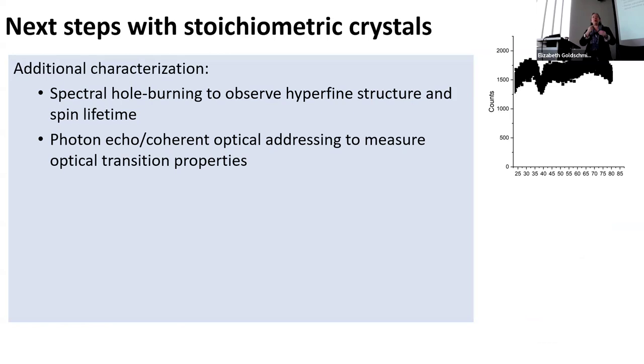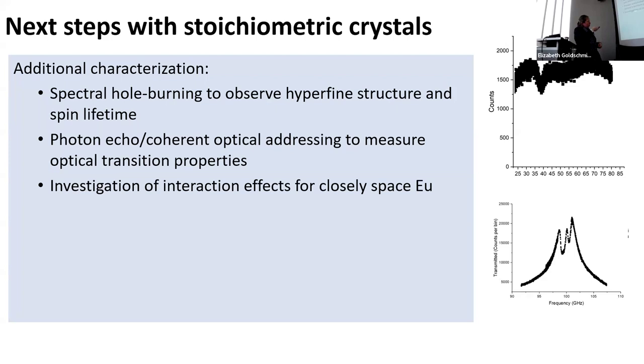Also, we want to do coherent measurements to measure that optical coherence time and see how radiative it is. The lifetime's a millisecond and a half. What's the coherence time? How close is it to that lifetime? We're also seeing, because in that one crystal we accidentally grew the spacing was really close, and we think we're seeing interactions. Depending on certain regimes, we're seeing this multi-peak structure, which we think is interactions between the nearest neighbor europium atom. We want to try and figure out what that is.